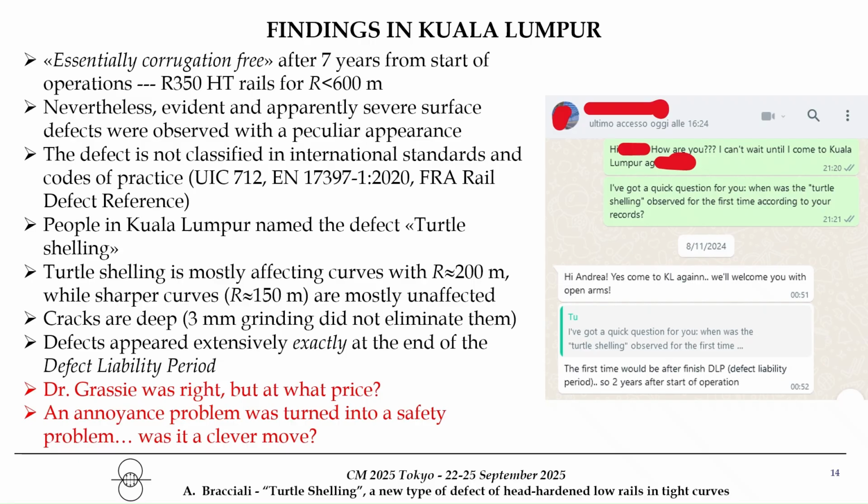We don't know how deep those cracks are, but certainly are deeper than 3 millimeters. And I was told, but I can only report what I was told, that some cracks are even 20 millimeters long, deep into the rail head, and they had to remove some rails. But you have to believe me as I had to believe them, so I have no proof for that.